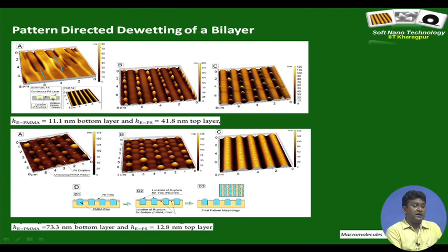And here again Rayleigh instability sets in, but you still get an undulating thread, and you can in fact carefully, by removing one of the layers, examine that the bottom layer ruptured and resulted in an array of droplets, over which the top layer was showing continuous but undulating threads. Very fascinating physics, and very rich physics in fact.